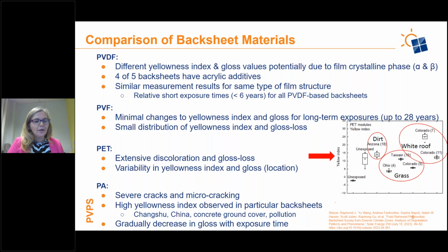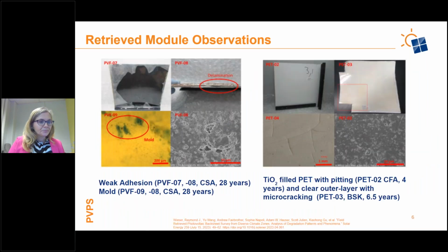For PET, we had extensive discoloration, yellowness index, and we also had a wide range of variability in the yellowness index. For polyamide, we saw the typical things that we have discussed all over the literature: severe cracking, microcracks, high yellowness index changes, and we also had a decrease in gloss with exposure time.